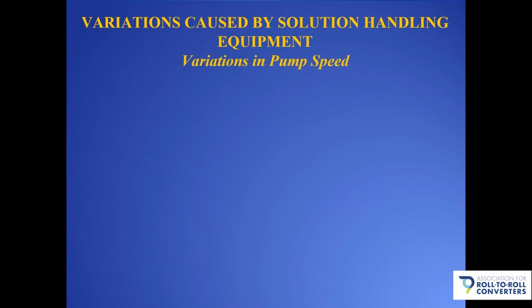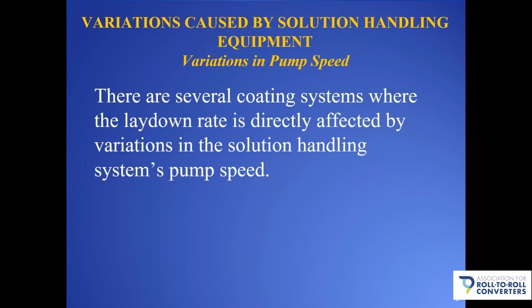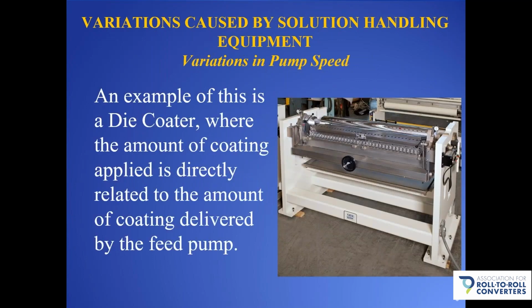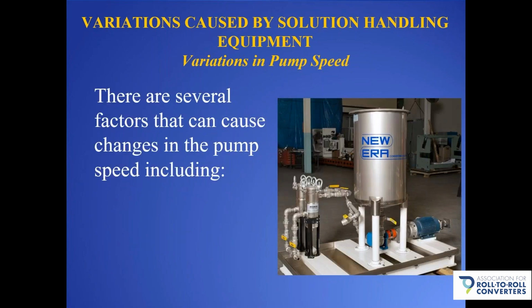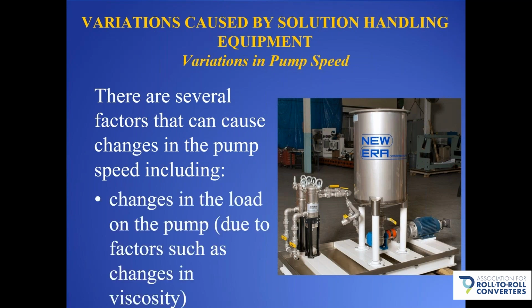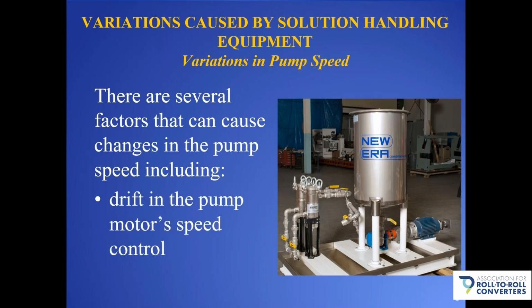So next, let's talk about variations in pump speed. There are several coating systems where the laydown rate is directly affected by variations in the solution handling system's pump speed. An example of this is a die coater like you see here on the right, where the amount of coating applied is directly related to the amount of coating delivered by the feed pump. There are several factors that can cause changes in the pump speed, including changes in the load on the pump due to factors such as changes in your coating viscosity, or drift in the pump motor's speed control.